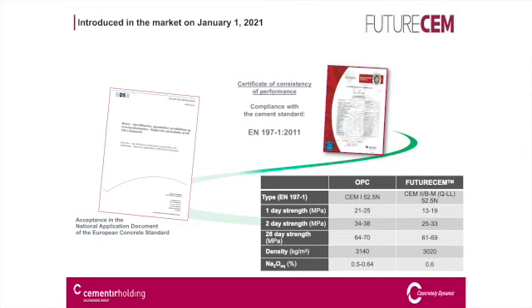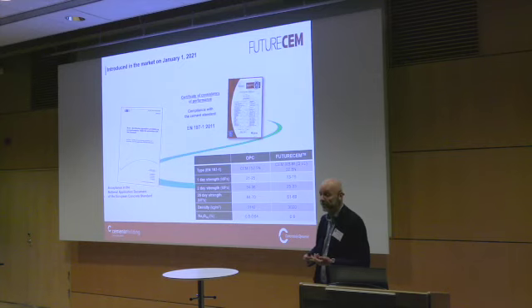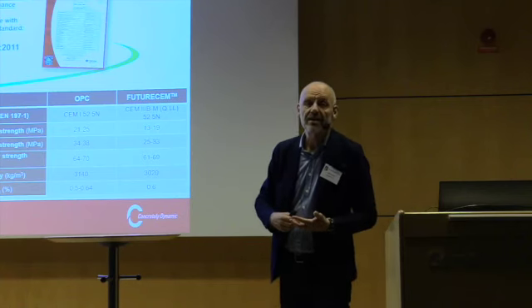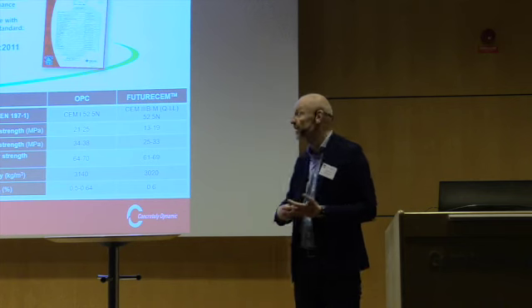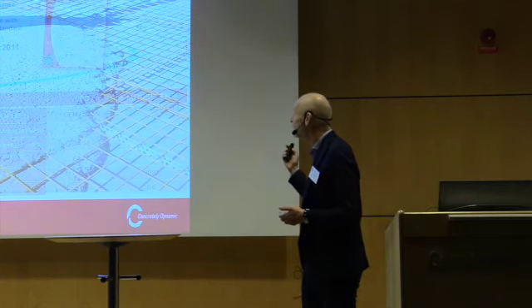And here are the specifications of the FutureCem as it is today. It is a CEM II/B-M (Q-LL) 52.5, so that is actually a rather high strength cement, even though we have 35% clinker replacement. Our one-day strength is slightly lower than the normal OPC, which is the main cement type until now in Denmark, but the 28-day strength is very, very close. You can also see the alkali content is equivalent to the standard cement.